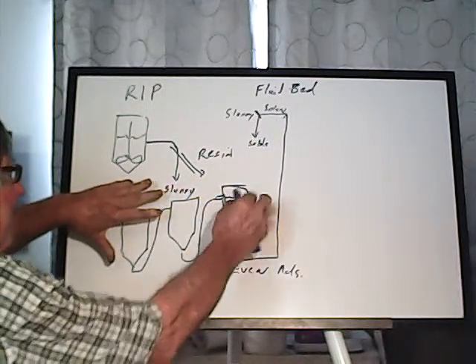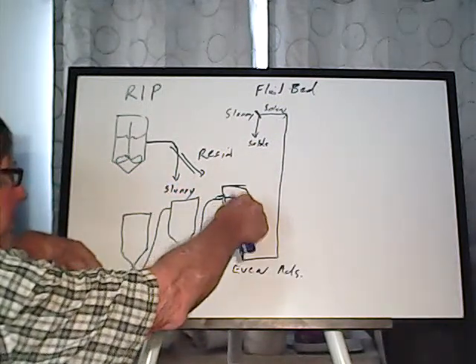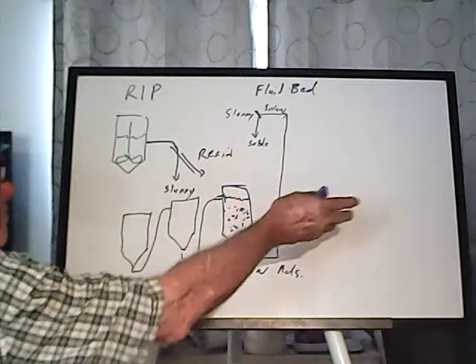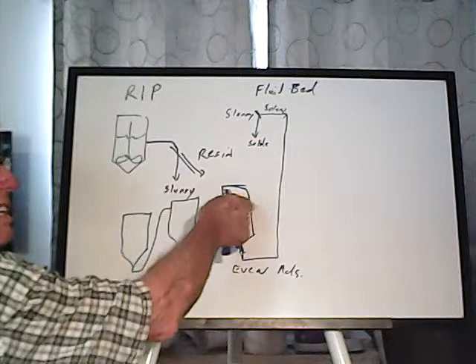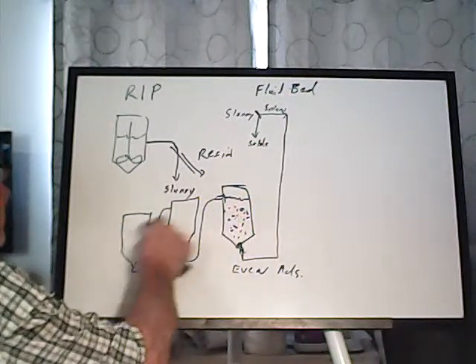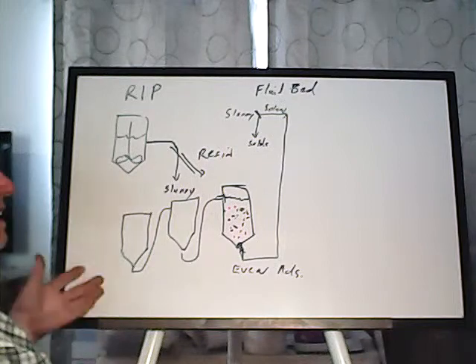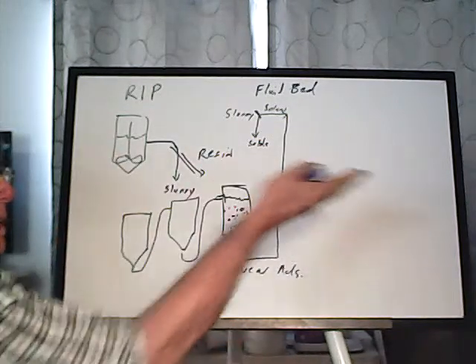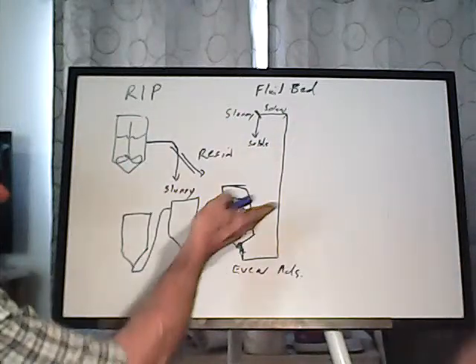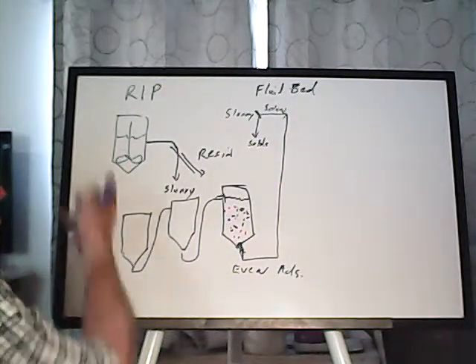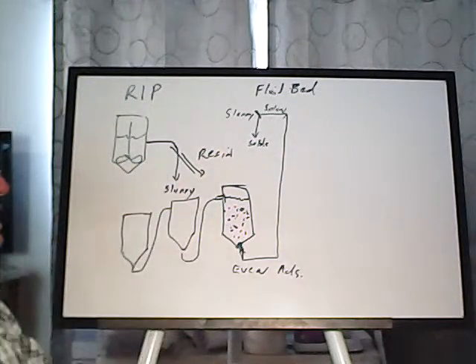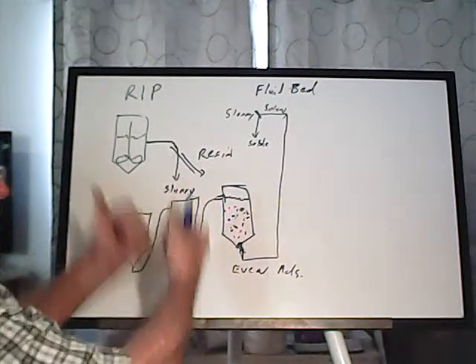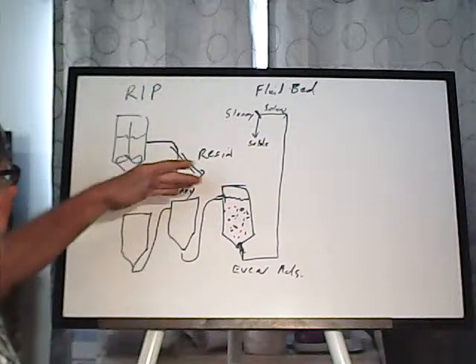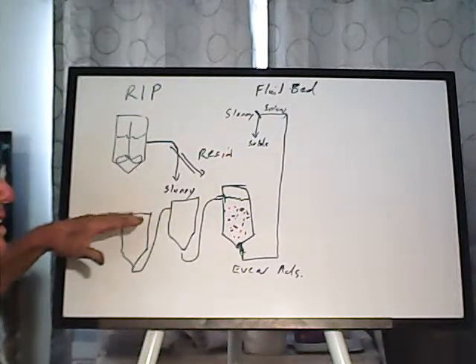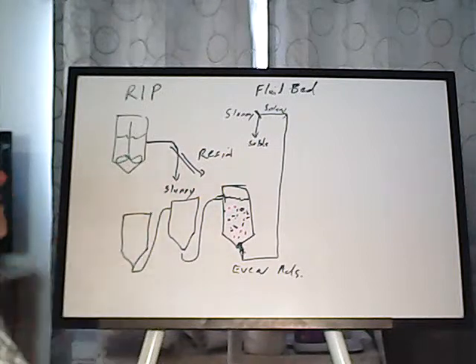And as this gets loaded, then you'll take this column or the resin out of the column, whichever you do, and strip it, and then you move the resin upstream. So the resin from this column goes to here, and the resin from this column goes to here. In the case of the mine I used to work at, we had these columns on pallets. So we had a big rack, and we'd literally just forklift them over to the stripping thing, and move them. And in 30 minutes, they're back running. The pumps are back on. Have hoses and quick connects. Now, the negative to this is that it takes more resin.